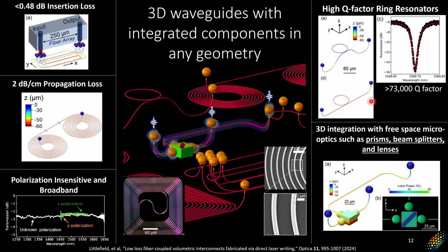What's the rule of thumb for the dn/dT of these? Does it follow the material you're patterning into it, or the CTE of the microstructure? Yeah, that's something that we're working on measuring now to get very accurate data on, so I don't have a good answer for you. What I can say is that we have enough design freedom here to compensate for essentially as much dn/dT as you want. We've been doing some designs recently for a lens that goes between 4K and room temperature and has no change in performance, assuming polymer levels of dn/dT, which is quite high.